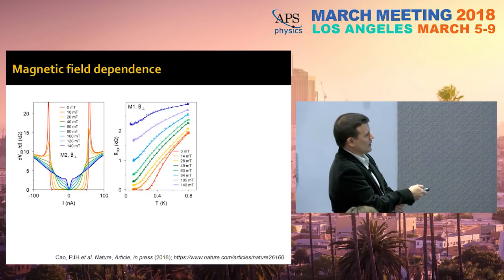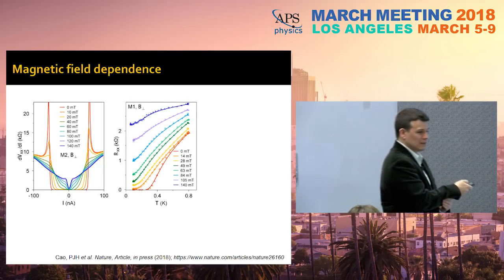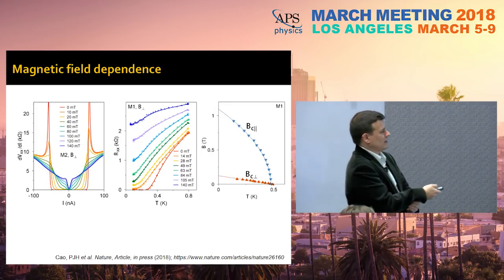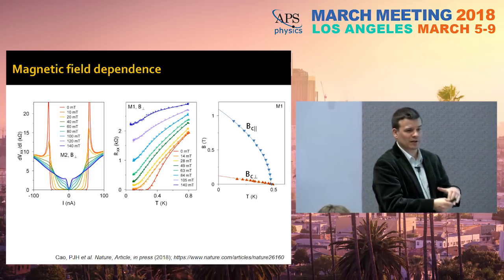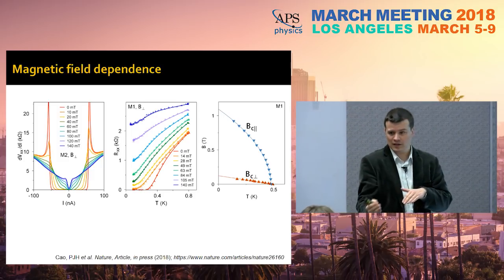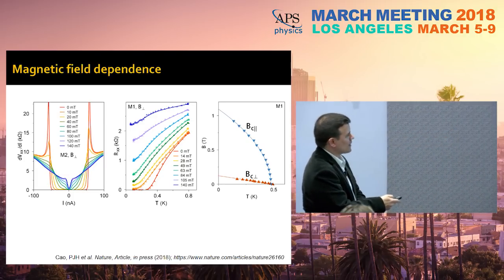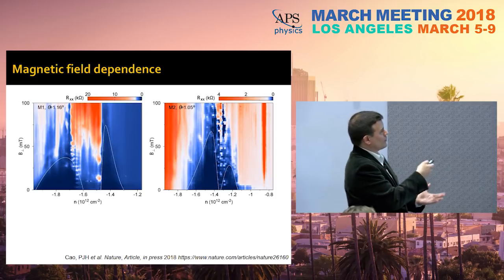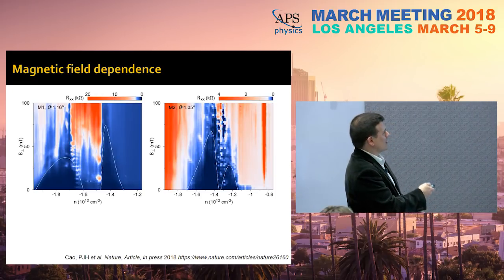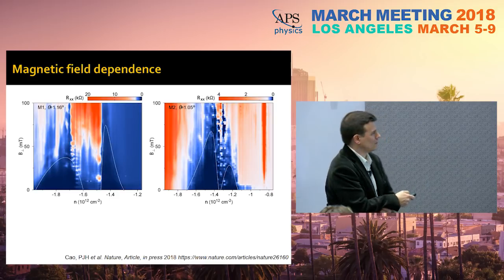We can look at this behavior as a function of temperature and magnetic field so that we can extract our superconducting coherence lengths. We can actually apply perpendicular and in-plane fields, okay? Of course, because it's a 2D superconductor, we can apply huge in-plane magnetic fields, as has been shown earlier today by many people. In fact, we can do all of this continuously, again, because we can plot these phase diagrams, now perpendicular magnetic field and density. These are for the 2 devices, and you have these superconducting domes in these magnetic field density plots, okay?